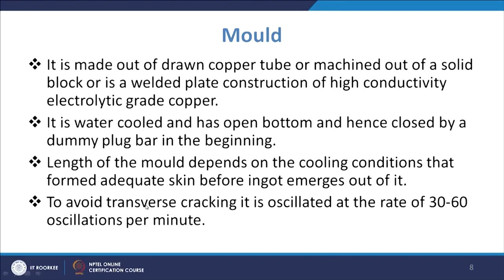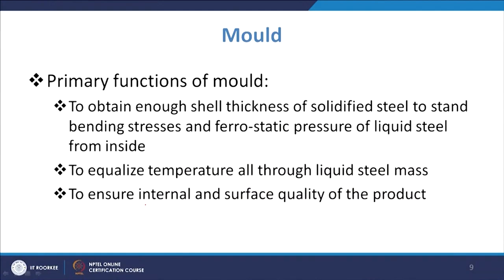Also, to avoid transverse cracking, the mold is oscillated at the rate of 30 to 60 oscillations per minute. We have already seen that you give that oscillation for certain regions, giving the negative strip, so that the product can leave the mold. Also in the mold we give lubrication. The function of the mold is to obtain enough thickness of solidified shell to stand bending stresses and ferrostatic pressure of liquid steel from inside.